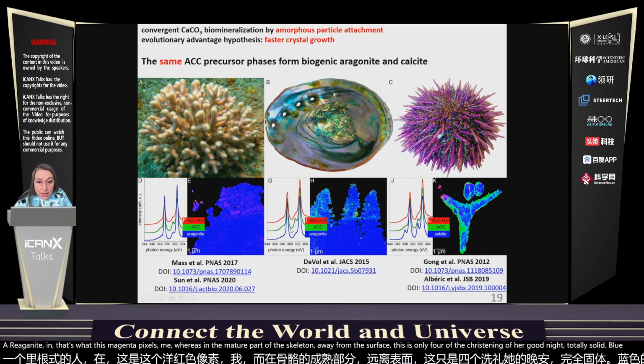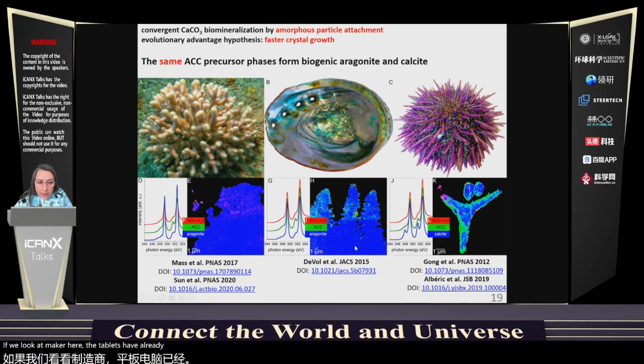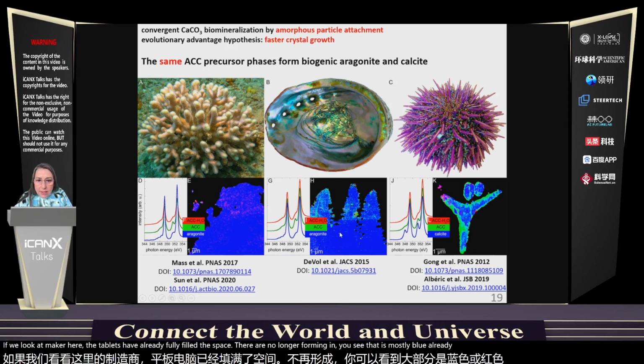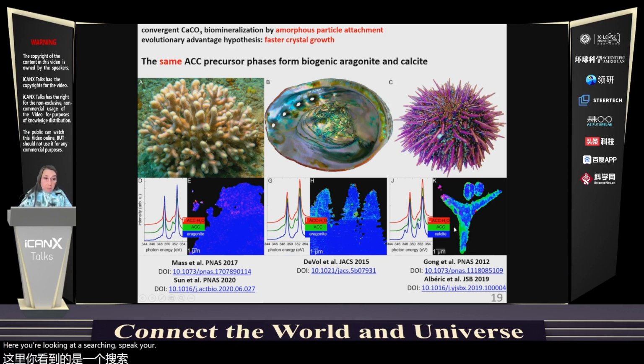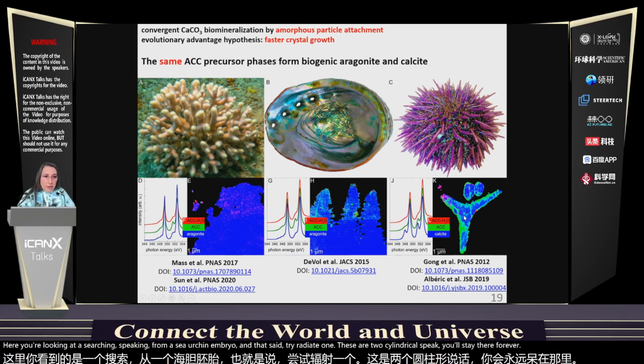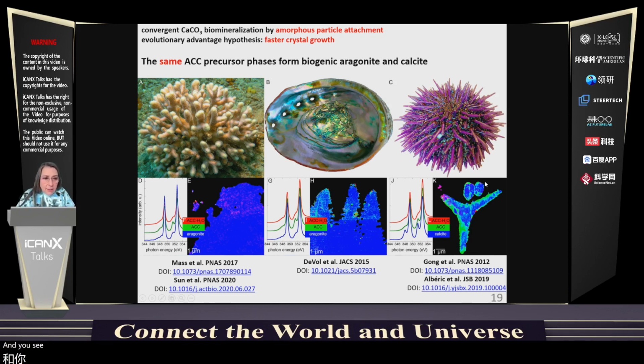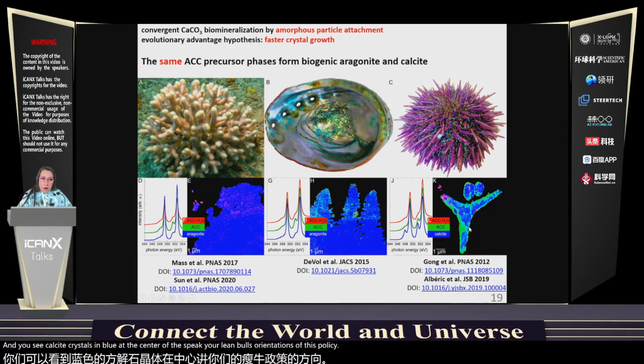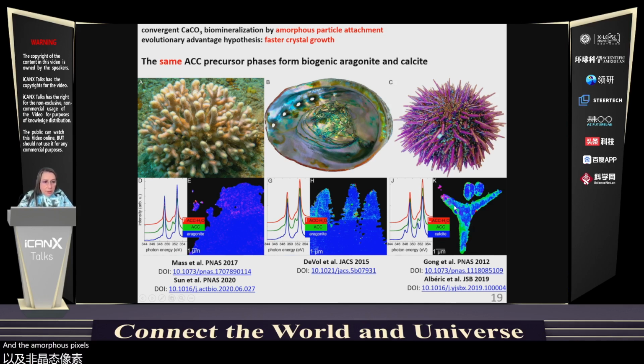Whereas in the mature part of the skeleton, away from the surface, this is fully formed crystalline aragonite, totally solid blue. If we look at nacre, here the tablets have already fully filled the space. They are no longer forming, and you see that it's mostly blue already. Whereas in these cones of still forming tablets, there are lots of amorphous pixels. Here you're looking at a sea urchin spicule from a sea urchin embryo, and that's a triradiate one. These are two cylindrical spicules that are perpendicular to the image plane. And you see calcite crystals in blue at the center of the spicule in both orientations of this polished cross section. And the amorphous pixels, mostly green, some red, some magenta, at the outer edges, which are the most recently deposited ones.